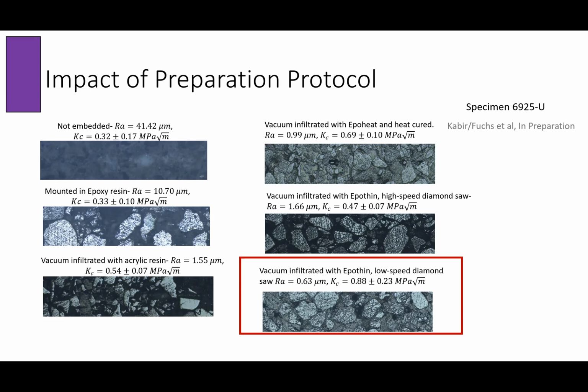But we also link it to the roughness because we want to have a criterion to assess the quality of our protocol. So the criterion is going to be the roughness. If you look at the 6 methods that we have, we started by just cutting it using a diamond saw and we don't embed it. And we have a roughness of 41 micron. Then we can mount it in epoxy resin. So we reduce the roughness, but we're still at 10 micron.